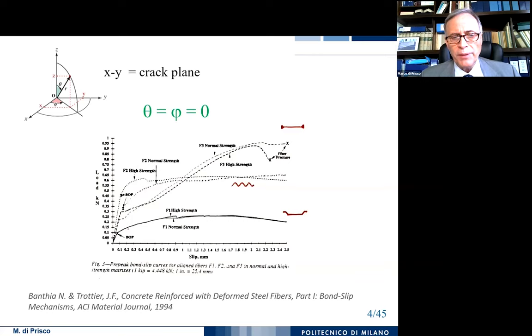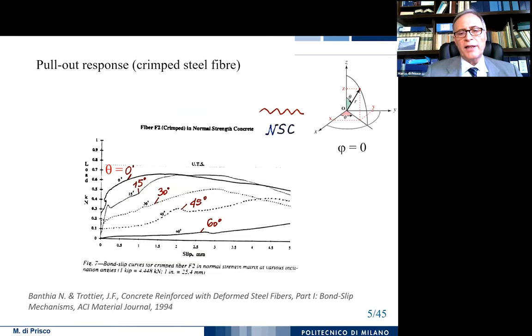A long time ago, in 1994, Banthia and Trottier looked into different types of fibers and, showing different pull-out tests, explained to us that if you change the shape of the fiber, you could have very different curves, load versus slip. And here you see some examples. Theta and phi correspond to the angles of the fiber with respect to the normal to the crack plane, which is XY. So you see that the shape gives us a different curve, so a different branch. Of course, if we also change the inclination, in this case for instance adopting different values of theta for the same type of fibers, you could also have a different response in terms of load and slip. That is a very important concept to immediately understand.